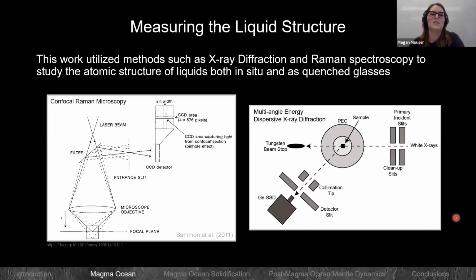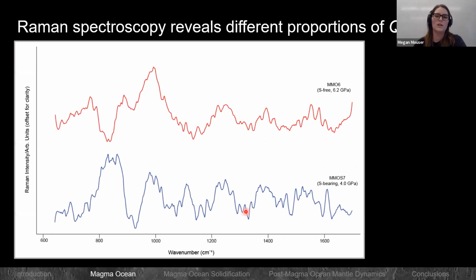So there are different methods that you can use to look at liquids or amorphous materials. You could use Raman microscopy, which you can do on glasses, the recovered glasses, or you can do in situ analysis with the multi-angle energy dispersive X-ray diffraction, and that actually is with the PE press at the beamline. What I'm going to show you are two Raman spectra that we took of two different glasses. In the red, we have sulfur-free, and in the blue, we have the sulfur-bearing. So pretty much immediately, you can tell that there are some differences with the spectra of these liquids.